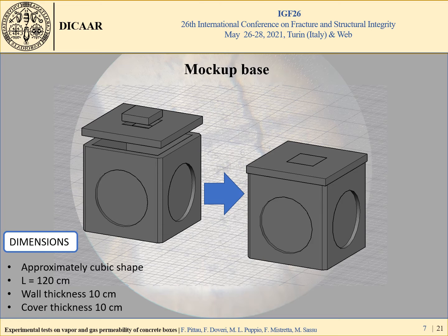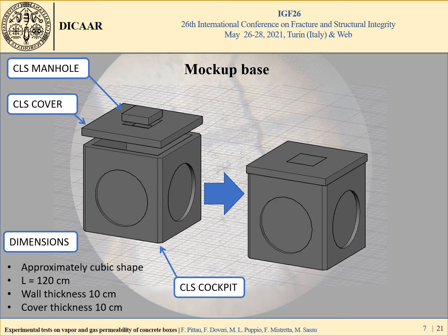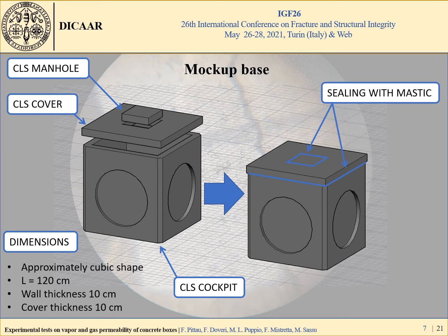Four specimens with approximately cubic shape are tested. The mock-up for the test is arranged using a concrete cockpit, usually applied in water discharge management. The cockpit was closed by a sealed cover and a sealed manhole. All the parts were sealed with mastic. The wall and the cover thickness is around 10 centimeters. That makes the test conditions very hard for the external coating.